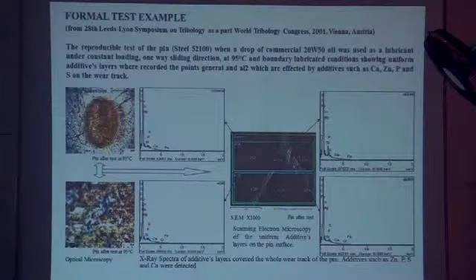Well, this is the example of the pin. This is the optical microscopy, and in higher magnification it's very colorful here. With SEM you see that calcium, phosphorus, and sulfur exist everywhere. It's very nice, well done. So this is the formal conditions, and we did other tests taking these conditions into account.